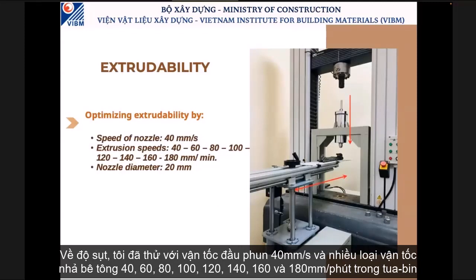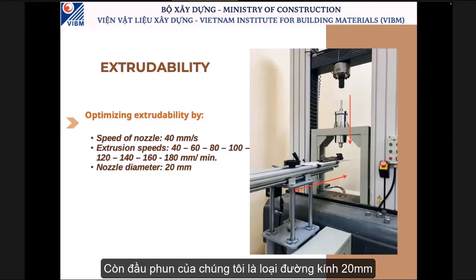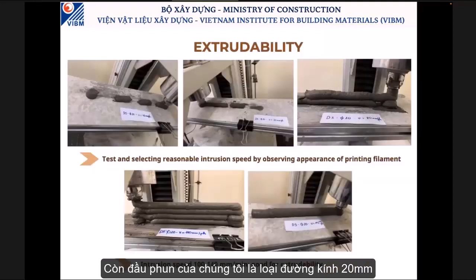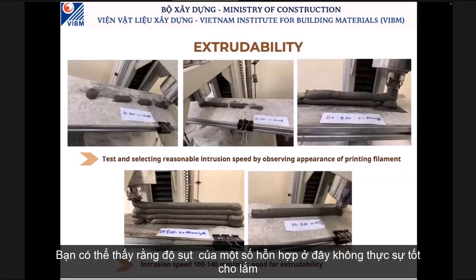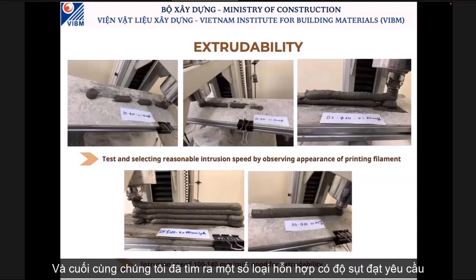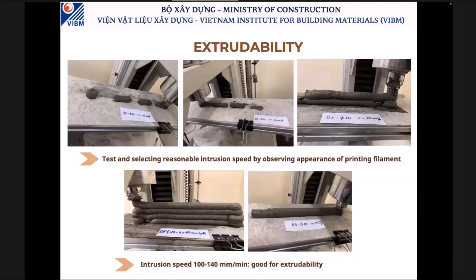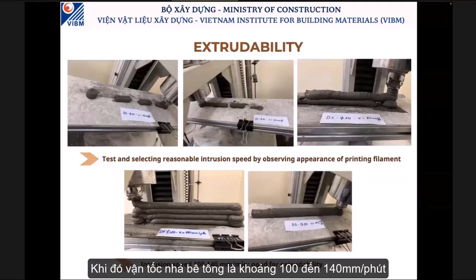For extrudability, we try to optimize by variation of the speed of the nozzle, with extrusion speeds of 40, 60, 80, 100, 120, 140, 160, 180 millimeters per minute, with 20 millimeters per minute interval. The nozzle diameter we test is 20 millimeters, and you can see here the extrudability. Some mixes are not really good, and finally we find some mixes have good extrudability. And the extrusion speed should be 100 to 140 millimeters per minute.